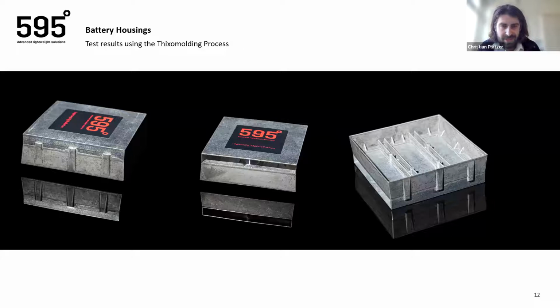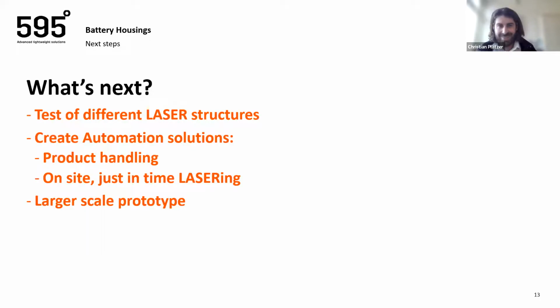Here are some nice pictures of the prototypes that we have cast in Germany. We are quite satisfied, but we are not yet there. There is no big prototype yet. So for the next things we are going to do, we are still testing further laser structures with different geometries. We are already working on solutions for the automation of this process, because we also found out that the laser structure needs to be quite fresh before overmolding. So there needs to be a just-in-time lasering next to the die casting machine.